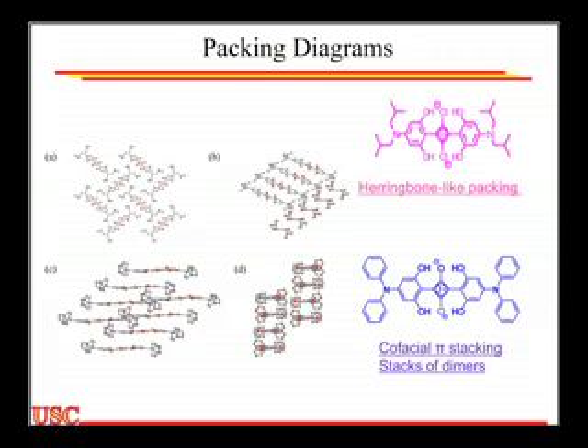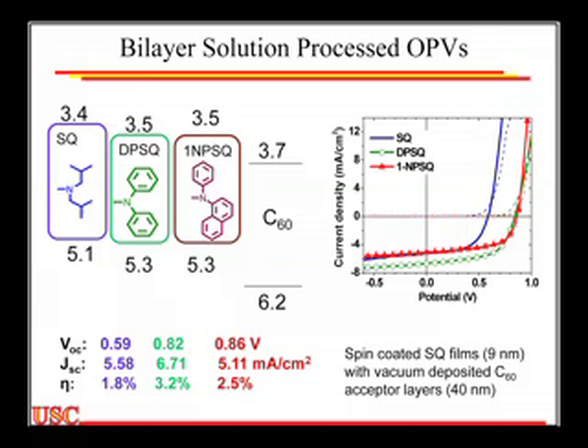But if we look at the packing diagrams for these, they're really quite different. The isopropyl derivative forms a pretty standard herringbone packing. Nothing special. The intermolecular spacings are pretty long, and there's not a lot of intermolecular contact. When we go to the diphenyl derivative, it forms a slip stack of dimers, where the spacing is about 3.5 angstroms. The packing is not between the phenylene end groups; the closest spacings are between the squaraine cores. So it looks like we might be better off if we can induce this sort of crystal form in the films, in terms of both exciton transport and carrier transport.